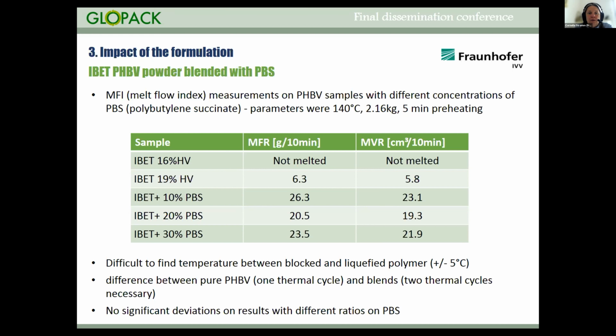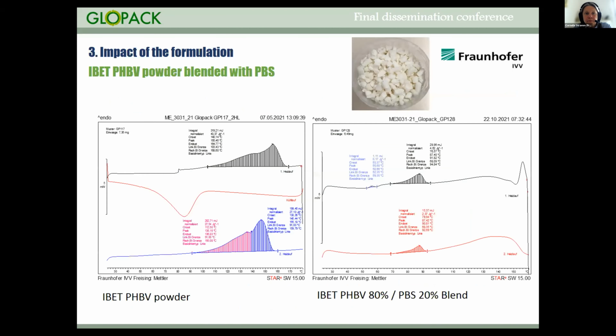And here it was difficult to find the right parameters to compare the different materials under the same conditions. But you can see that the blend materials show higher values of the MFR in comparison to the pure project material. And with different ratios of PBS, we have no significant deviation in the results. And on the next slide, you can see some melting curves.